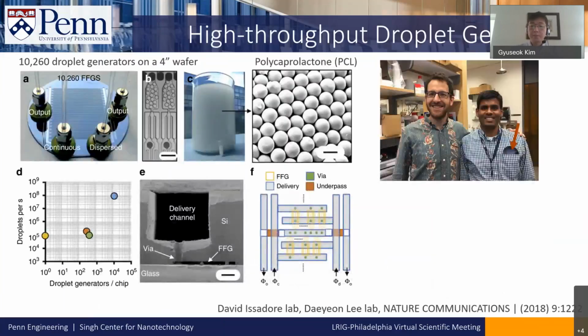So here at Penn, Dave Issadore's lab and Daeyeon Lee's lab made droplet generators with silicon. As you can see on the left side, they put more than 10,000 droplet generators on a 4-inch wafer. Then they did wafer bonding with glass and put in some continuous phase and dispersed phase, and they extracted the particles. In the center of the slide, as you can see, they even made PCL particles with regular size. So they are all monodispersed.